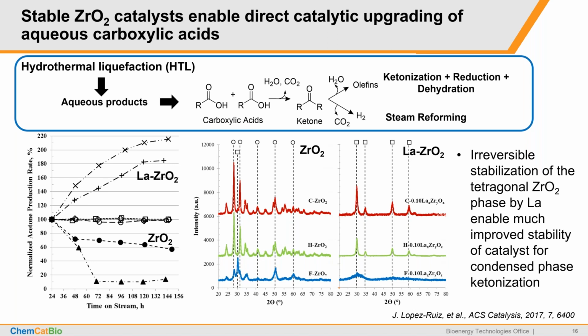And the team actually spent a lot of effort to mitigate this catalyst deactivation by using lanthanum doping to not only enhance the activity of this catalyst, shown on the left-hand side, but also prevent those phase transitions. Shown on the right-hand side, after using lanthanum doping, this catalyst maintains its tetragonal zirconia phase in water or in carboxylic acid condition.